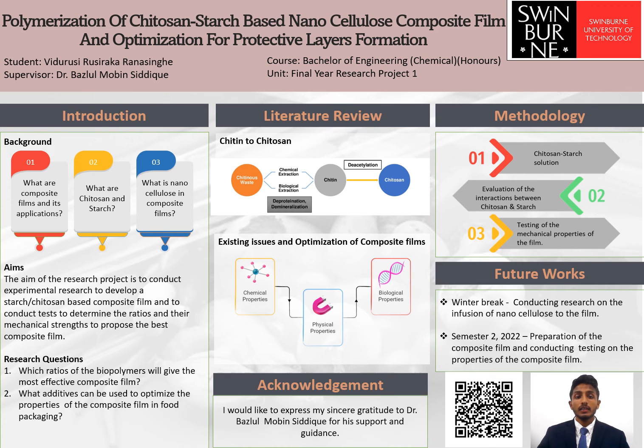The second part is where the interactions between starch and chitosan will be examined using FTIR spectroscopy, and the crystalline structure of the polymer will be further examined using X-ray diffraction. This will give a better idea of the compatibility of the starch and chitosan as a composite film and the use of additives to make the film more effective.